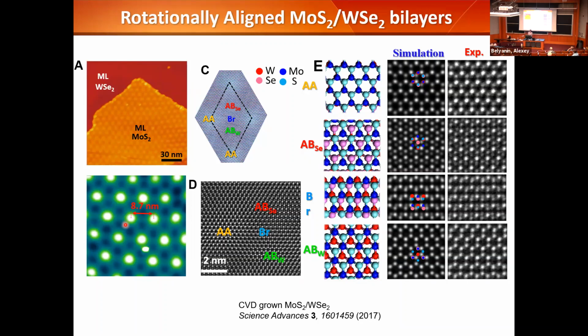So we knew the concept of superlattice before. We grow very thin layers and we build the one-dimensional superlattice. Now this gives you a way to construct an in-plane superlattice with many easy controls. And the beautiful thing is there are many van der Waals materials. Some are magnetic, some are ferroelectric, some are semiconductor, others are insulator, others are semi-metal. You can stack arbitrary combinations of them on top of each other because you do not have to satisfy the lattice matching condition. You just have a gigantic library to build your heterostructure with. And then we rely on theorists to tell us what are the most interesting combinations to put together. Otherwise, we can never exhaust them in the laboratory.